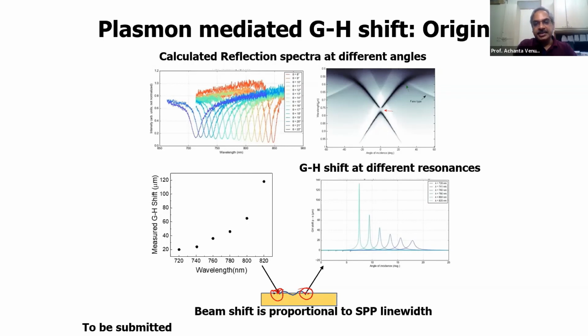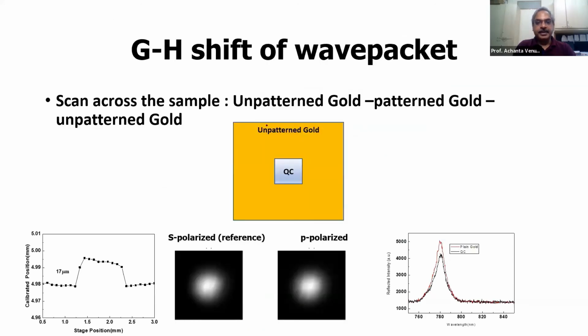So the plasmon-mediated Goos-Hänchen shift is because of this plasmon propagation. Because the plasmon lifetime and the inverse of the line widths which we measured match pretty well, basically the beam shift is proportional to the plasmon line width, right?